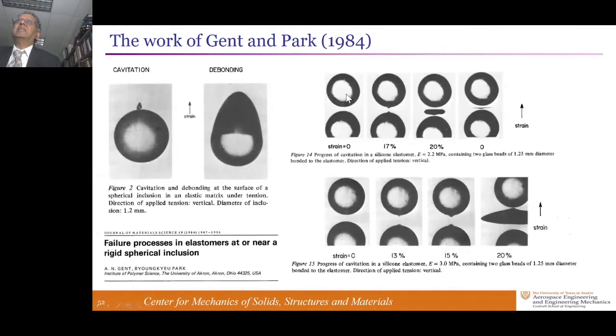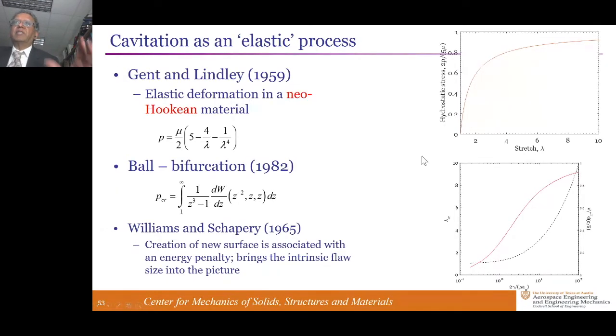He performed an experiment in 1984 where he had 2 beads confining the region in between them and tried to obtain images of what happens as a function of the global strain between the 2 beads. And he found that some things happened near the poles of the beads, but then something transitioned and occurred in the midline between the 2 pieces, which turned out to be a crack. There are multiple explanations for this, and I don't have time to go through all of them. One is that it is an elastic instability of a spherical cavity in a neo-Hookean material. And there are bifurcation calculations to show that if the pressure level reaches 5/2 of the shear modulus of the material, a small cavity will grow in an unrestrained manner.